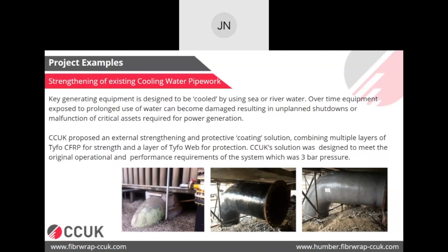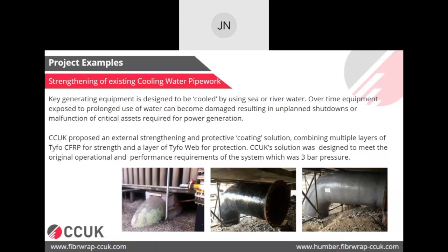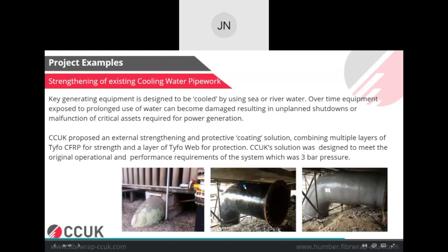So they had a fear that one day they will lose the whole pipe completely, and the outer concrete encasement, which is not reinforced, will be exposed to very high pressure, and they might have a burst out failure and lose the cooling tower completely. So this was more or less like a fail-safe kind of design. So they asked us to design this carbon fiber strengthening system to take the 3 bar pressure. So just in case they lose the internal pipe, there is still some sort of reinforcement outside which will stop the burst out failure. And that's what we have done. We applied the carbon fiber again in the hoop direction to increase its capacity and to provide a 3 bar pressure capacity, and also reinforce its concrete. And ultimately it was coated with again a waterproof coating.